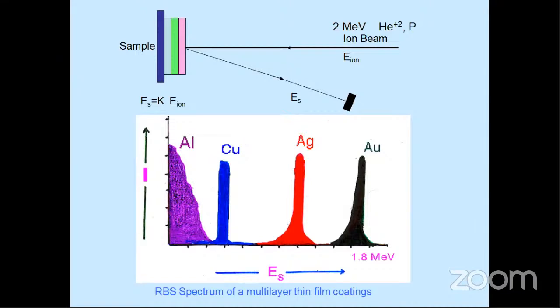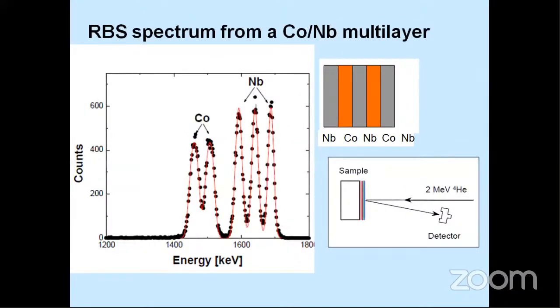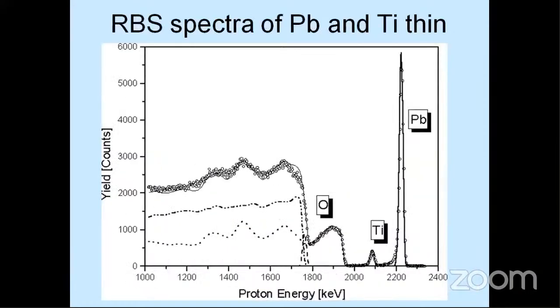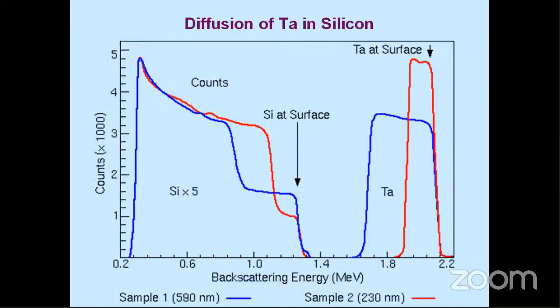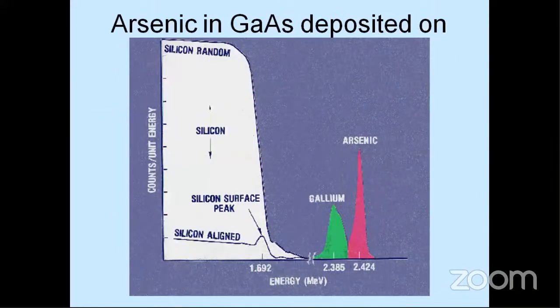In IUC Calcutta, IUC Delhi it is available. So if you are interested to study, you can use it, because it's also very useful for thin film technique. You can use it for measuring thin films. Suppose you have a multilayer thin film, with niobium, cobalt. So this is a very good technique for measuring the thickness of thin films, and the diffusion of these. So there are different applications of this technique. For gallium arsenide, if you bombard, you can see the arsenic peak separate and the gallium peak separate.